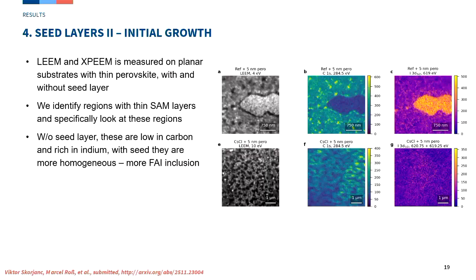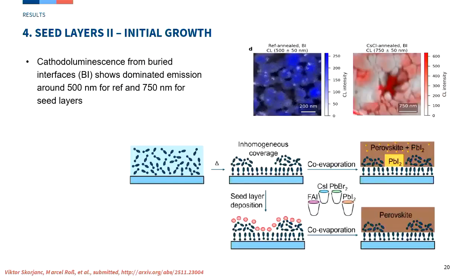Now if we form a seed layer first, you see it's much more homogeneous. Even if the seed layer is only 5 or 10 nanometers in this case, not a closed layer, it does form a much better perovskite to start with. So the initial growth is improved over time.